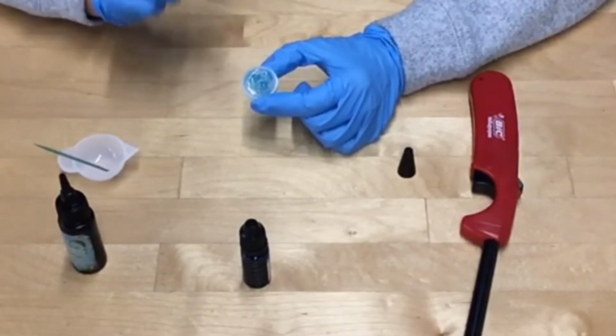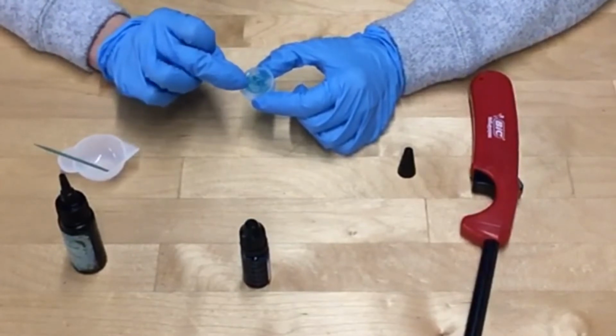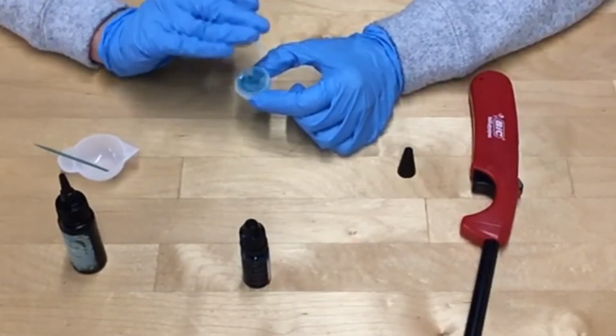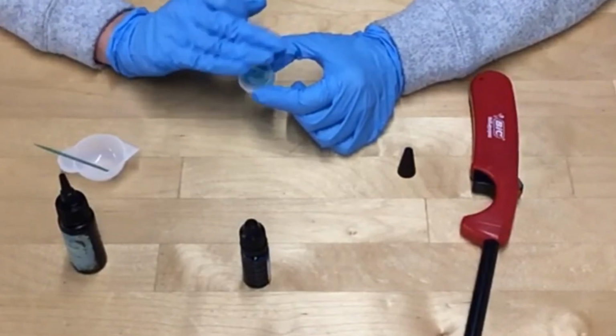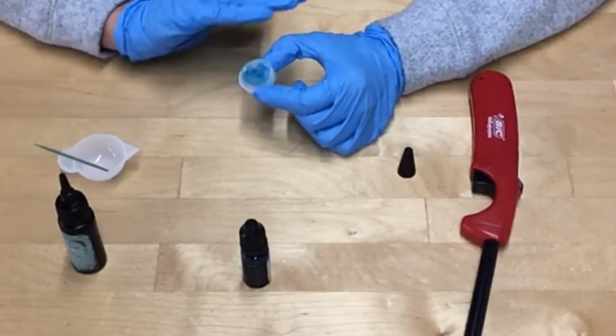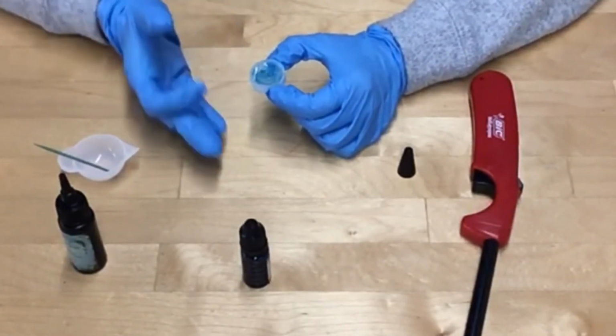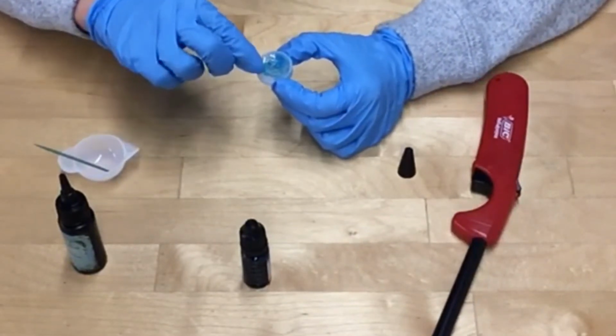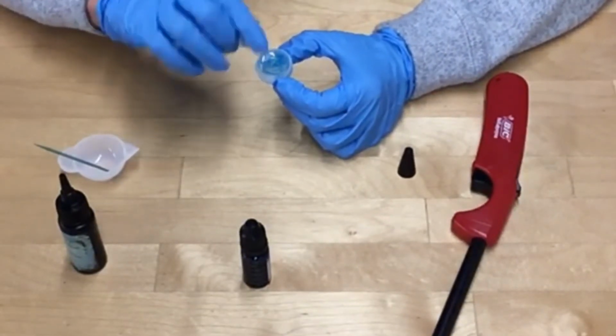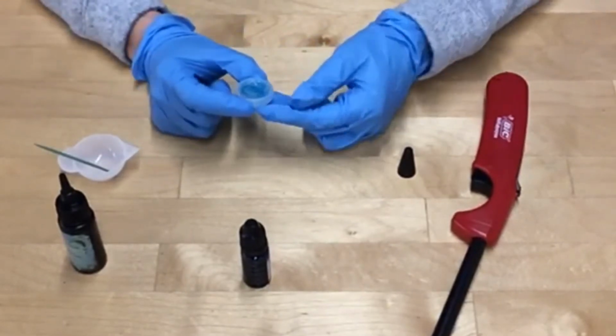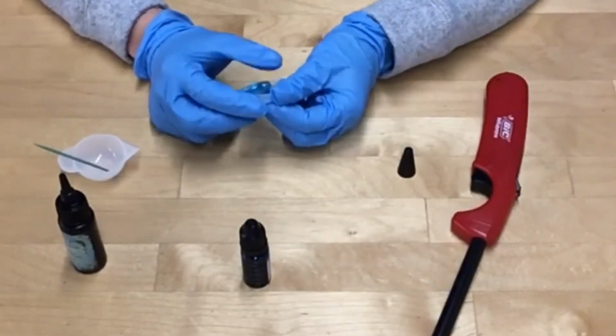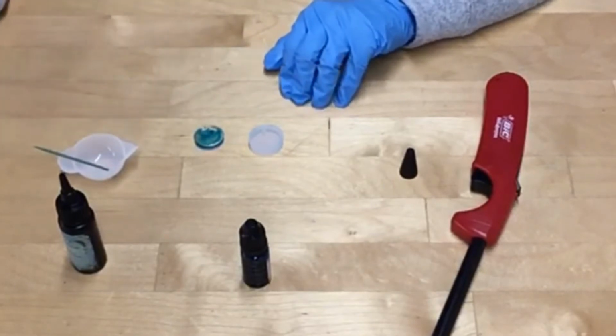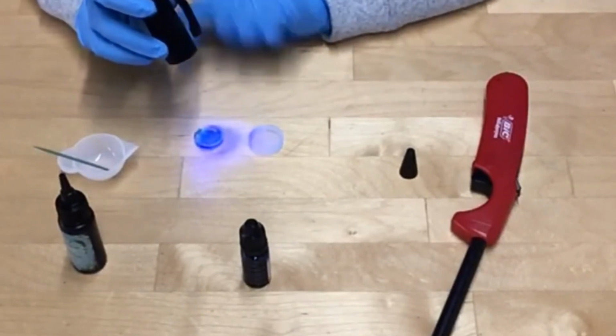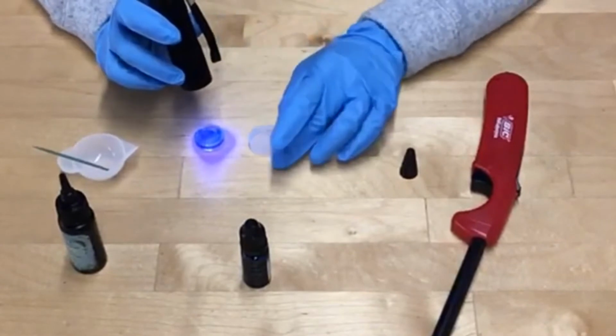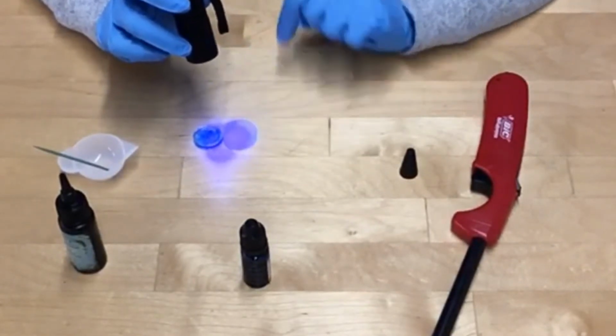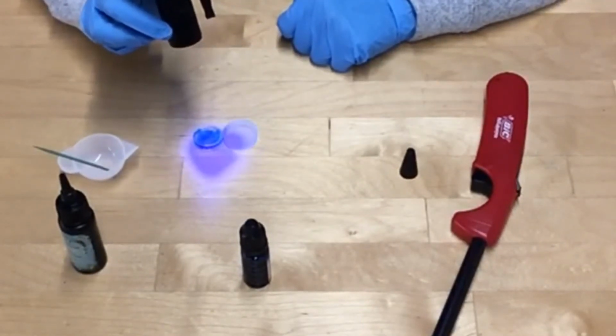Now, this is one of the trickier techniques because sometimes the dye at the top layer doesn't harden. So you might need to clean off extra dye with a wipe or a little bit of alcohol. Or another way you can fix this is by adding another layer of clear resin on top to seal that dye in. So I'm gonna remove this just like the other one. And then after removing it from the silicone mold, you can use your flashlight on the back side for another minute, and also to make sure any residue in the silicone mold has hardened.